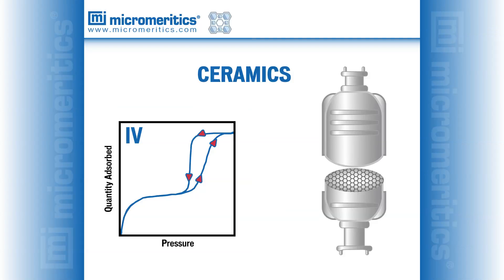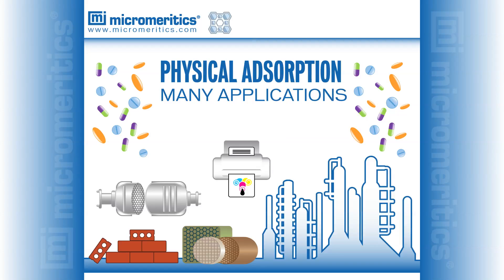The final product highly depends on the texture of the original materials. As can clearly be seen, material characterization using the physical adsorption technique can contribute to the understanding of the texture of any type of solid, as long as the solid is capable of physically adsorbing an inert gas such as nitrogen or argon. The adsorption isotherm generated by this technique enables one to determine the surface area, porosity, and total pore volume of solids, all of which are important properties that predict activity as well as selectivity of any catalyst without an actual chemical reaction needing to be performed.